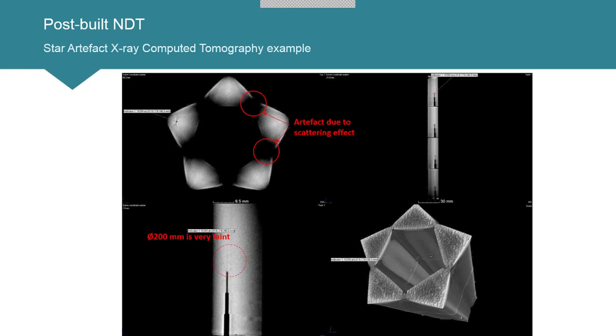more faint. But we have also cut up some of those, and that 200 microns is much better detailed than you see here, and that's due to the limitation of the X-ray CT resolution. So for that 200 microns, what's possible is just not as clear as in here, basically. Another thing that I'm highlighting is that X-ray CT has some difficulties, let's say, which are the artifacts. In this case, I'm showing artifacts due to the scattering of the sample. This is a very dense part, which makes these artifacts more visible.